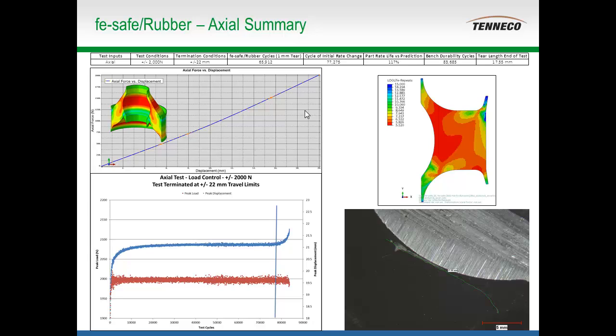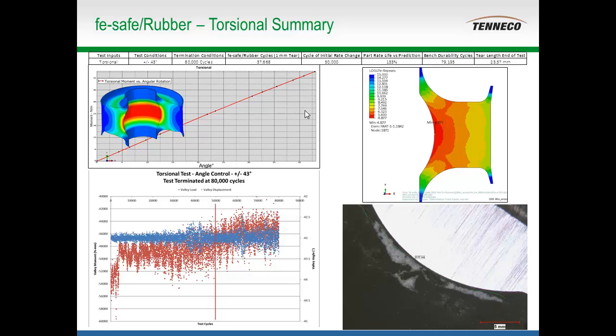So thank you, Will. When he flashed the 5-minute left sign, I kind of got rushed. So what I'm showing in these photos is we took the parts, sectioned them, and then actually mixed up some white epoxy that we injected down into the crack, and let it cure, froze the parts, and then polished them to allow us to take some photographs that would show, for presentation purposes, the crack location much more accurately. Took them into our microscope, measured the crack length, which I'm reporting in the various tables.